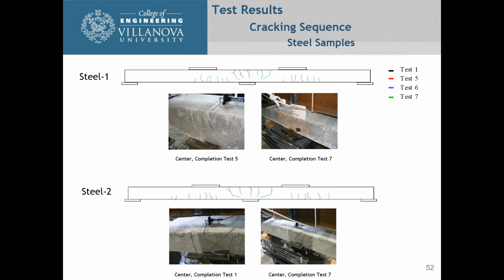And in test 7, where we finally got what we want to call failure, because we were not able to fail any of these to the point where you had a big failure of the beams. There just wasn't enough capacity in the actuator for it. But you can see the cracking patterns. You have flexural cracking on sample 2 here and here, and you actually have a shear fracture near the support.